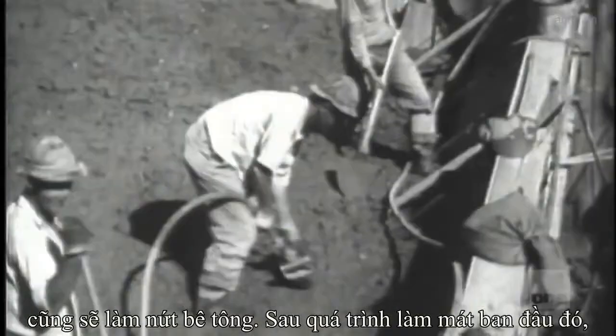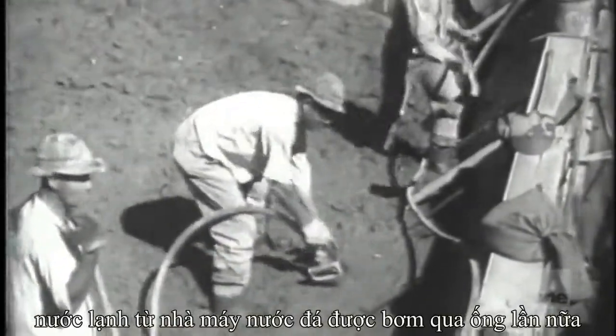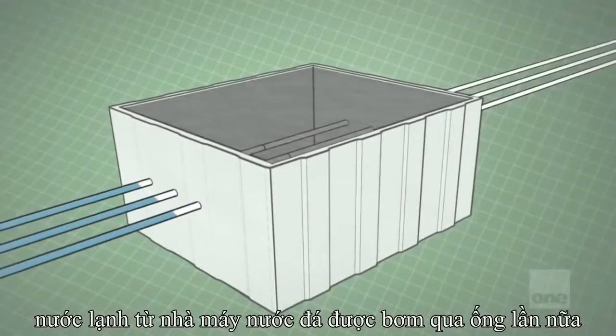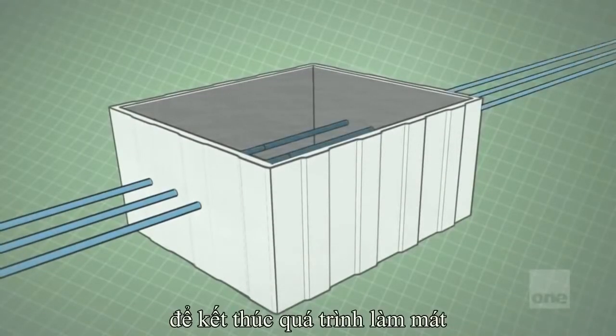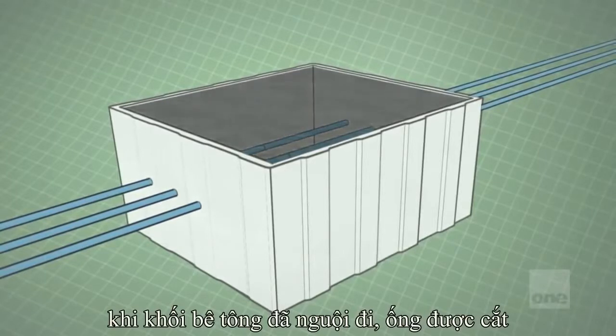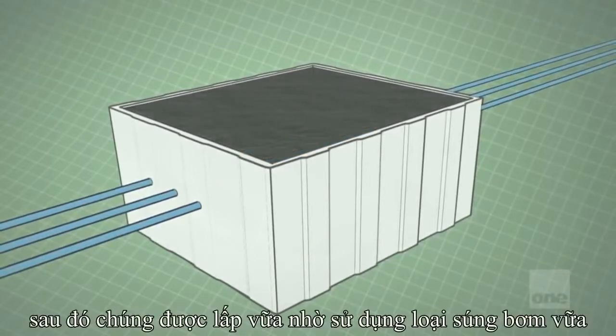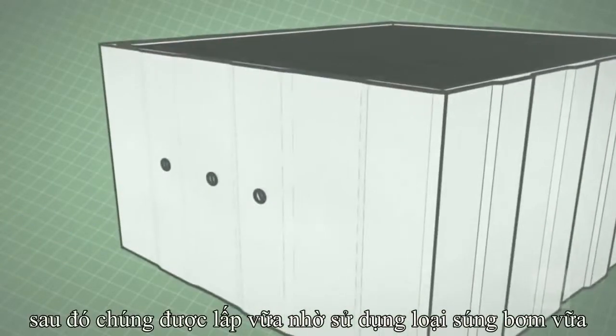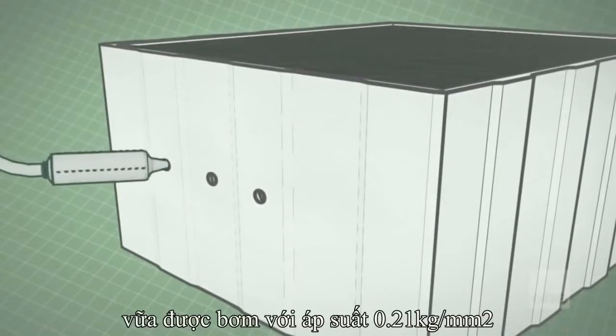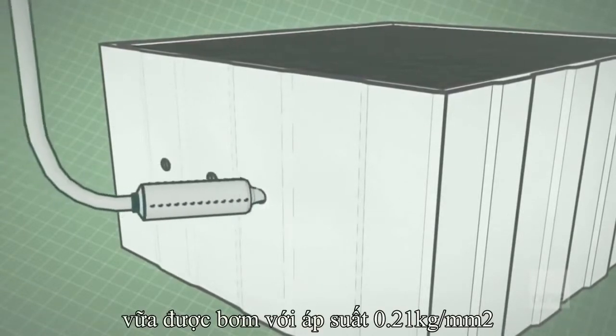After the concrete has received its initial cooling, chilled water from a refrigeration plant is circulated through the coils to finish the cooling process. As each block is cooled, the pipes are cut off, and they are filled with grout by pneumatic grout guns, pumping 300 pounds per square inch of filler.